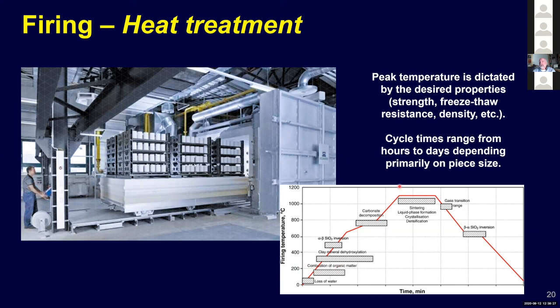The temperature is not bad based on Boston Valley's temperature, somewhere around 1100 degrees C is their peak temperature. So what happens is that you start at room temperature, you heat it up, and then there tends to be a little bit of a slowdown where you allow carbonates to decompose below 900 C. And then you continue up to your peak temperature and you'll hold there for a period of time. It might be several hours, depending. And then you cool back down. And then there's a slowdown at the quartz inversion temperature, which everyone believes is necessary, but actually is not. And then you cool the rest of the way down to room temperature. You are typically okay to open the kiln somewhere just below 200 degrees C. Best practice is to let it be as cool as possible before you open the kiln.